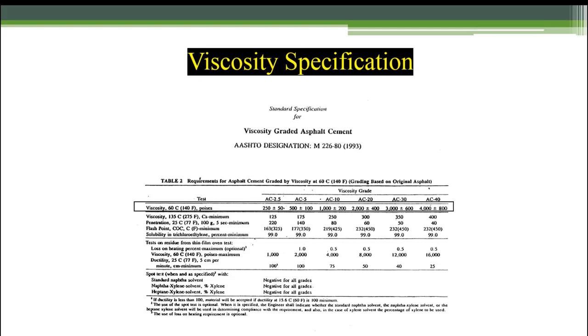We had a lot of truck traffic in Wyoming, and the problem with having a stiff asphalt is, in a thermoplastic material, it's great for stability when it's hot out, but what happens when it gets cold and extremely cold? That stiff material doesn't want to give, and the material's trying to contract. So on that minus 25, minus 30 degree morning at sunrise, guess what? You get cracking. So we'd go back and forth. It was kind of funny when you look back. We go AC 20. Rutting's a problem. Spec AC 20. Want to resist rutting.